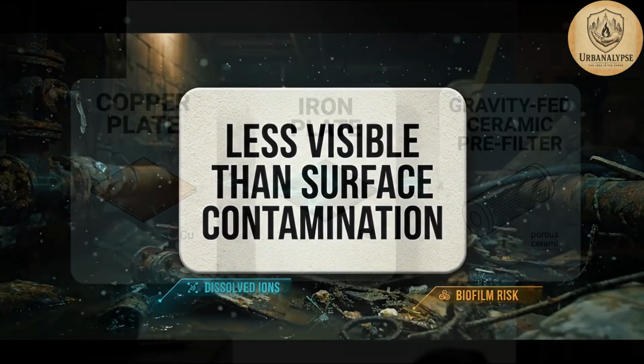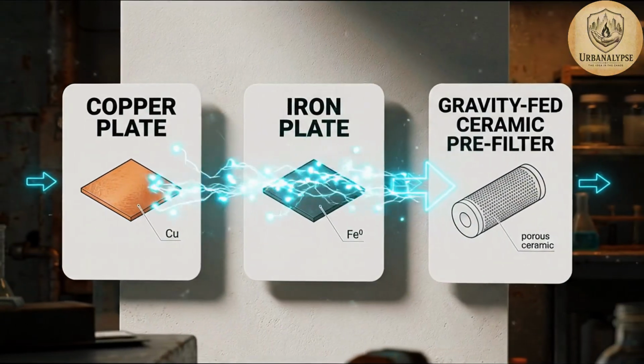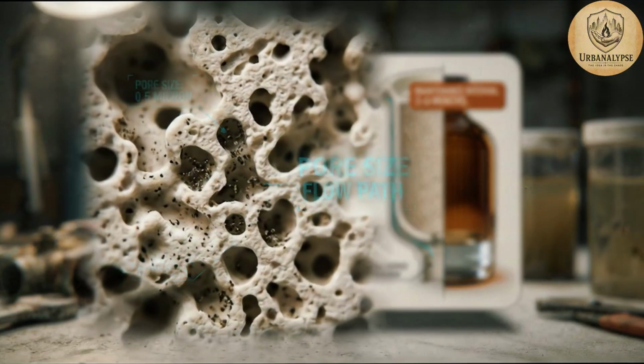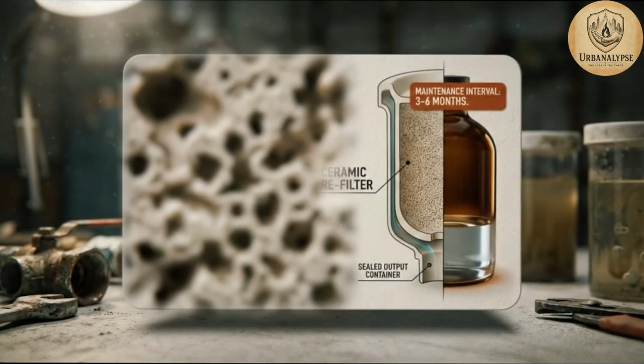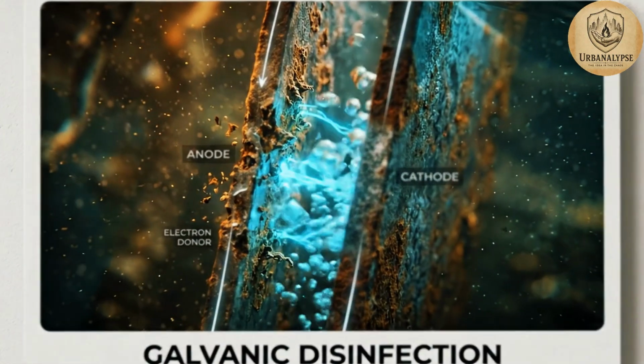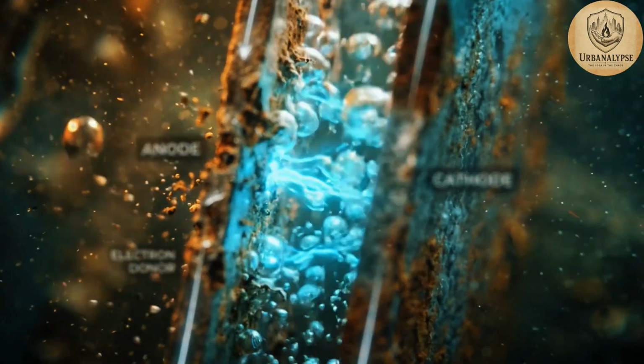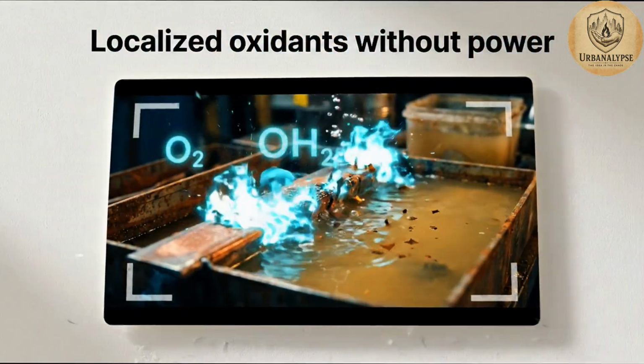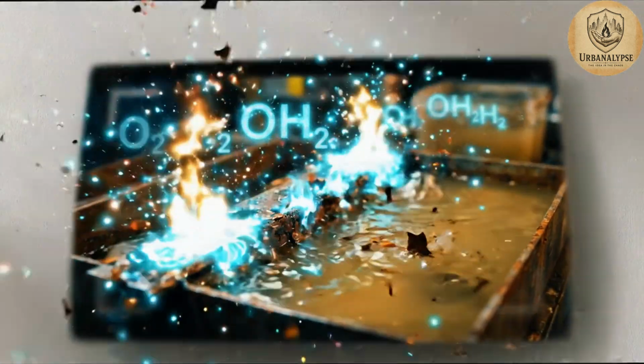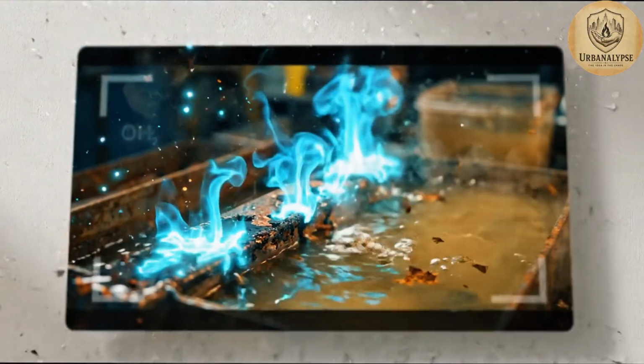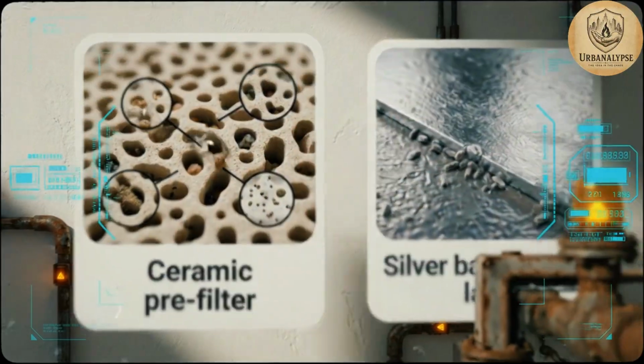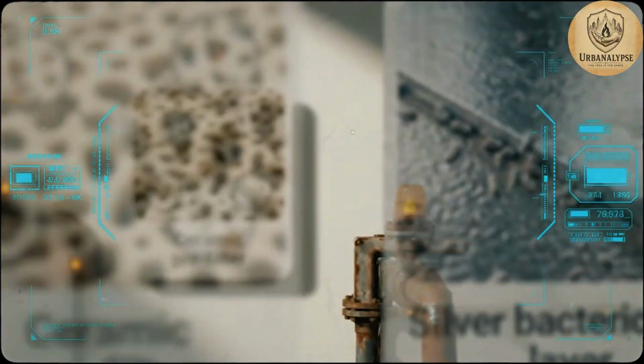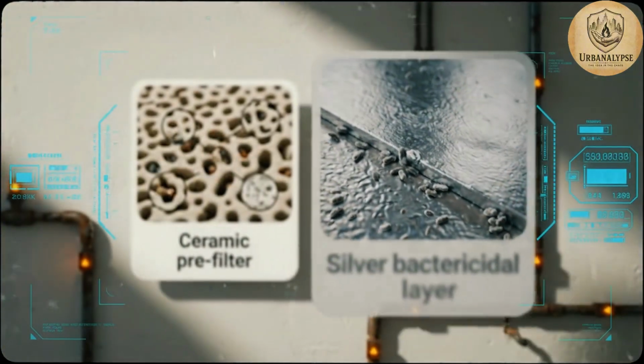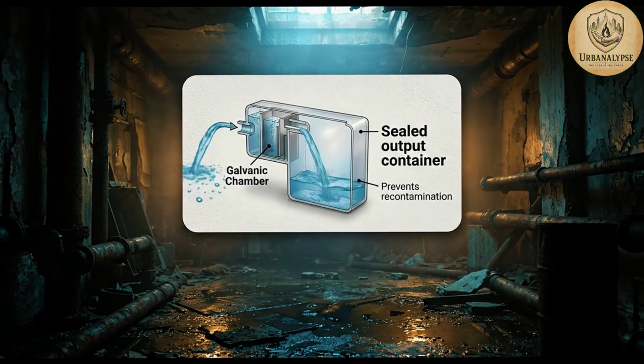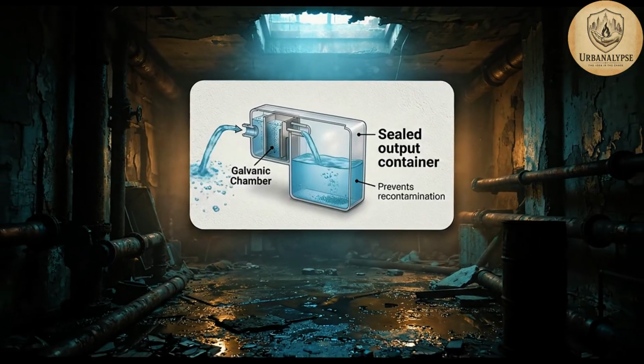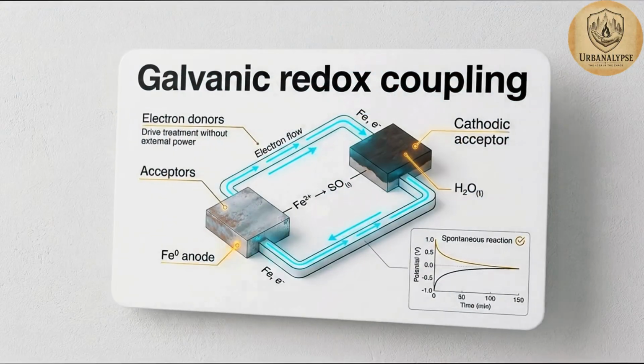The assembly: a copper plate, an iron plate, a gravity-fed ceramic pre-filter, a sealed output container. Galvanic chemistry between the plates drives ionic disinfection and generates localized oxidative species without any external power input. The ceramic pre-filter handles particulates and provides a silver-based bactericidal layer before water reaches the galvanic stage. The sealed container prevents recontamination after treatment.